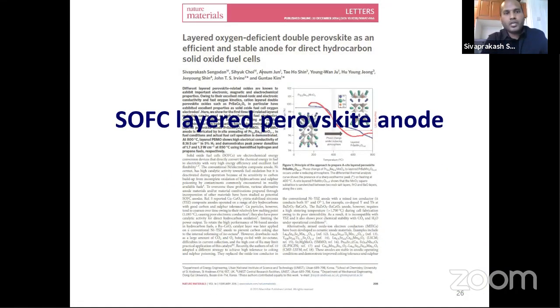Then we started working on layered perovskite materials to use as the anode material in solid oxide fuel cells. We found that praseodymium, barium, manganese oxide works as a very good anode material for solid oxide fuel cells.